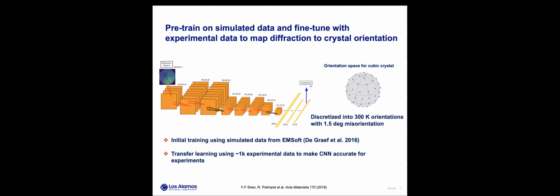So as an initial training step, we generated 300,000 simulated diffraction patterns from cubic symmetry orientation space with 1.5 degree disorientations using this EMSoft software that was developed by Professor Marc De Graef's group at CMU. And we trained our CNN, and we knew that the simulation-trained network would struggle with the experimental patterns, because the experimental patterns have inherent noise in the images, and also the forward model that we use to generate these synthetic images has missing physics. So because of these discrepancies, the simulation-trained network would not produce high accuracy reconstructions.